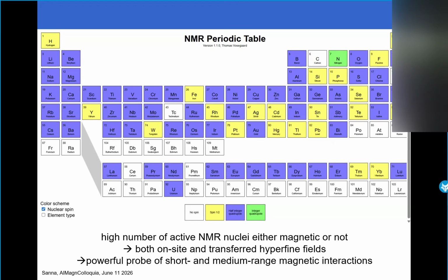And this helps because it means that we have a high number of NMR active nuclei, either magnetic or not, which means that you can probe both on-site hyperfine fields, for instance if you do NMR of iron, which is typically magnetic, or transferred hyperfine fields, maybe measuring the NMR on another nucleus, which is not magnetic in that system, but which feels the transferred hyperfine field from the neighbors. And so this is a very powerful probe of short and medium range magnetic interactions.